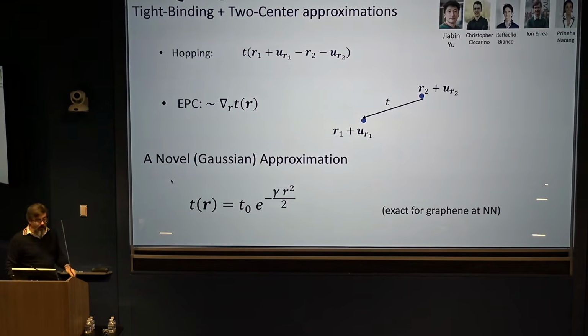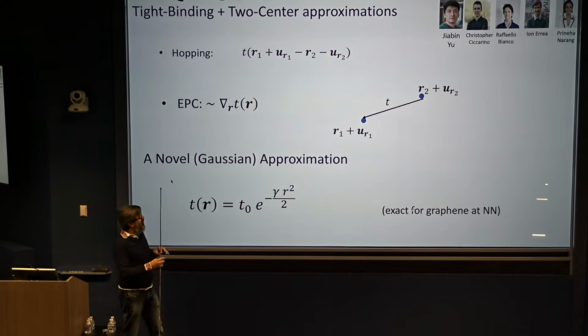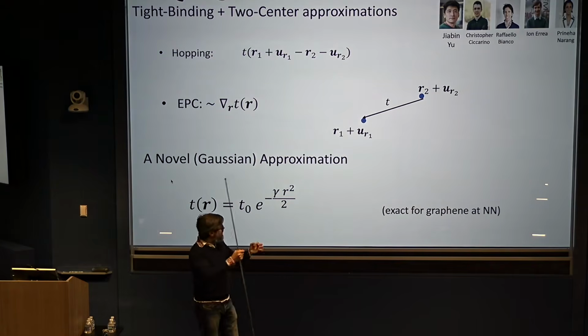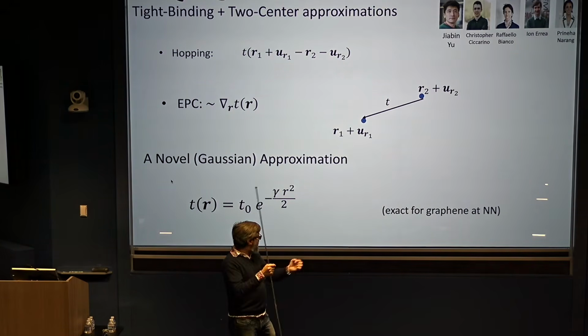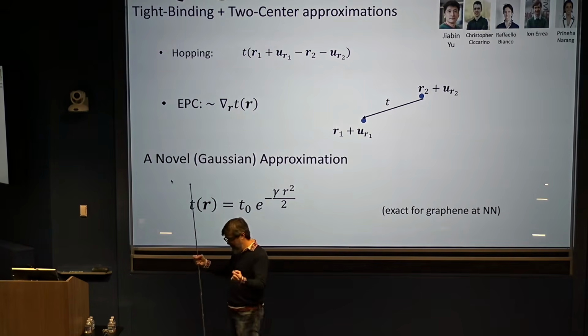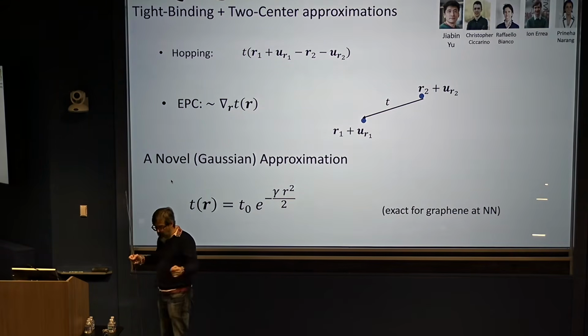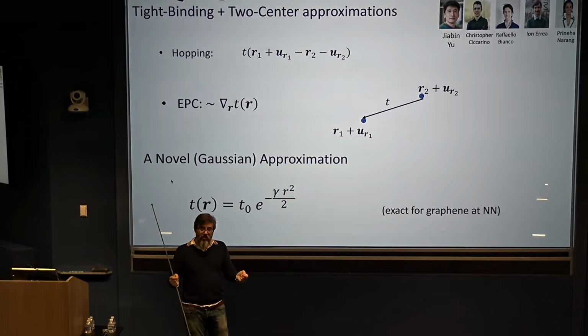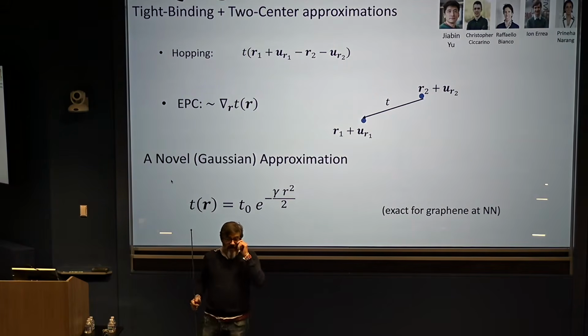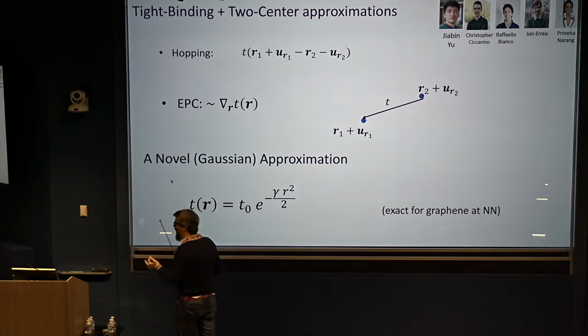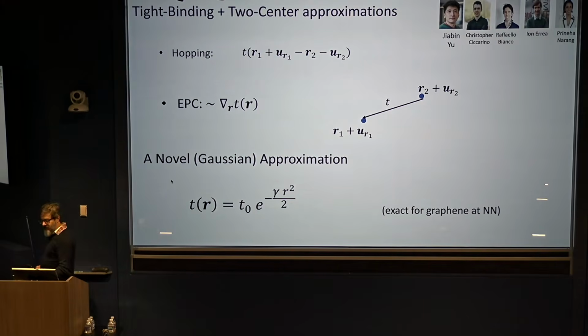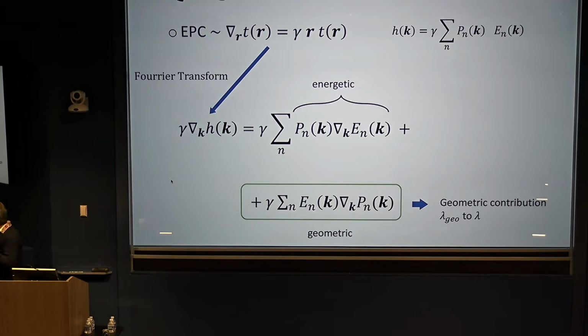Now what we wanted to do is, again, to get some sort of a theoretical model of the electron-phonon coupling. And this is a theoretical model that we get by just assuming that the orbital overlap is a Gaussian between two orbitals. It's not a Gaussian, it's usually e to the minus r, but if you assume it's a Gaussian, you have analytic expressions, and that's how we do all the analytic stuff in MgB2 or the other superconductors. We just assume this, and once you have this, then you can immediately get an approximation for the electron-phonon coupling.